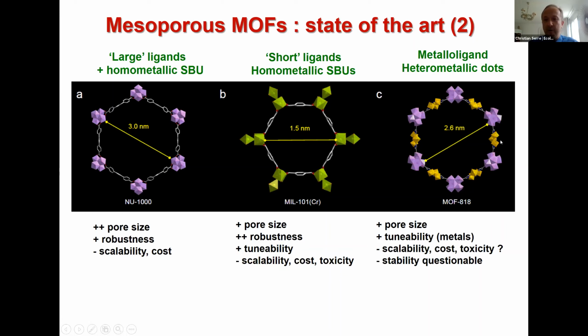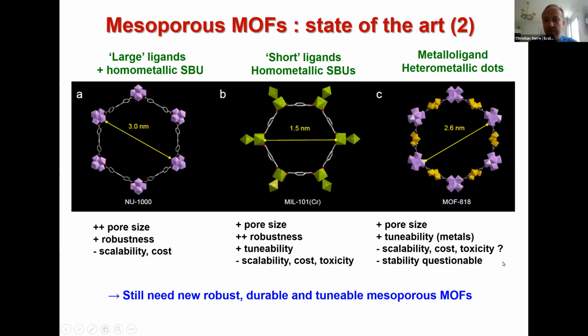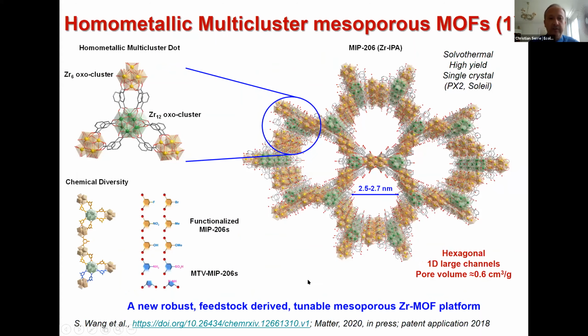But I think here there's a problem of stability, because the copper and the zirconium have very different stability issues. It means that as a whole, if there are interesting mesoporous MOF that can probably go to the application, like MIL-100 iron, there's still a need of robust, durable, but also tunable mesoporous MOF. So this is a recent result that is under press.